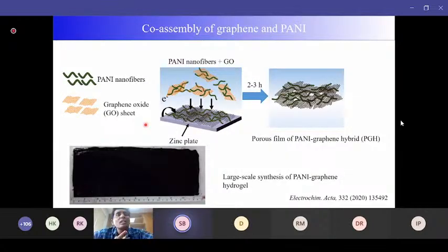And in this direction, although the areal capacitance is high, the question is whether we can increase the areal capacitance to a much higher level, because the areal capacitance was around 33 millifarad per centimeter square. And we already know that pseudocapacitive materials like polyaniline and polypyrrole have a very high pseudocapacitance because of surface reactions. So can we couple this polyaniline nanofiber with the graphene oxide sheets? In this case, we use a similar strategy. We just mixed the polyaniline nanofiber with graphene oxide, and polyaniline also has a pi structure in it. So polyaniline can make some pi bonding with this graphene oxide structure.